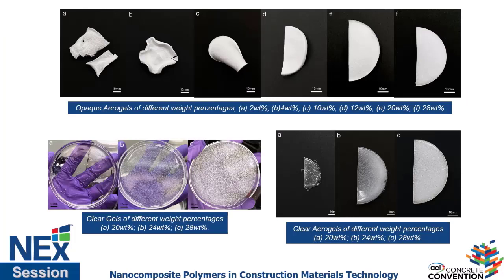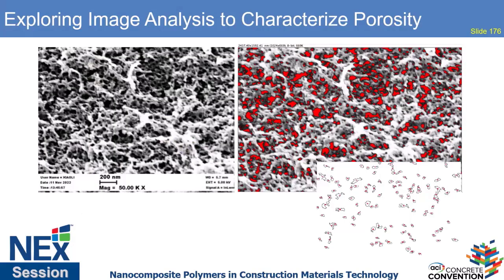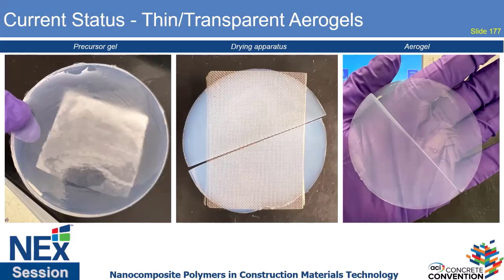And so these are the issues we have to get over. We also have to deal with bubbles and other things for transparency. But what happens is at the end of the day, these aerogels show some very unique porosity structures, and we're getting some very uniform porosity in them, which is very exciting because the gels are very uniform, the structures are very uniform, and ultimately this is where we're at. We're able to make very thin film aerogels that have the Rayleigh scattering effect that you would see for a silica aerogel, and they're not deforming as much anymore. So we're successful in reinforcing these structures. We're successful in making them thin and getting this transparent structure.